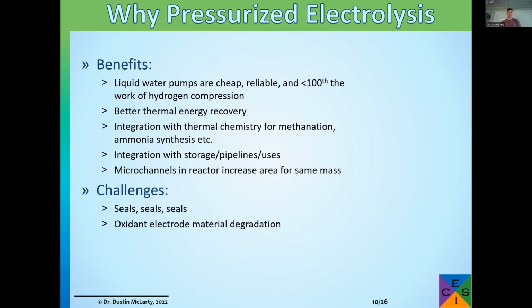So the challenges associated with pressurization are always the same. It's sealing the thing. Seals are bedeviling when you go to high pressure. So that is a major challenge. Then we also have thermodynamics working against us in some cases, and primarily at the oxide electrode, you see a lot of material degradation for most of the strontium containing perovskites onto a YSZ cell.